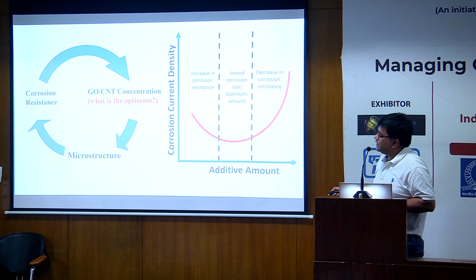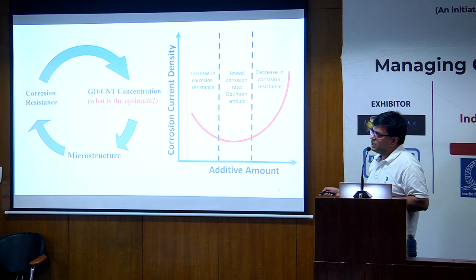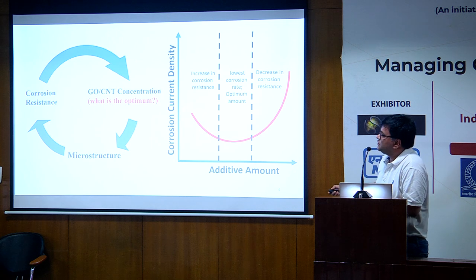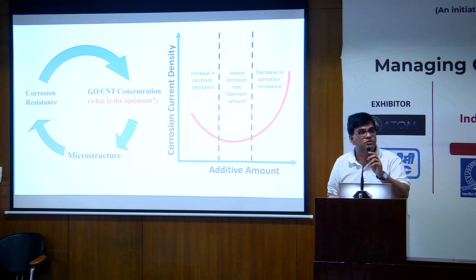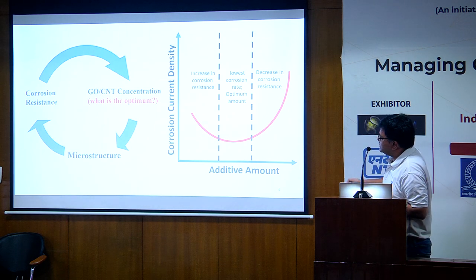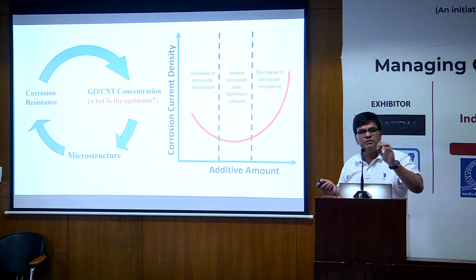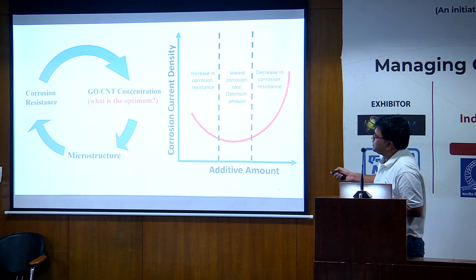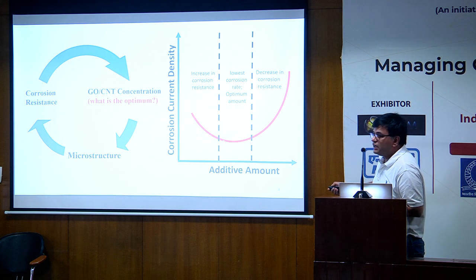What we have done is study the corrosion resistance behavior or corrosion rate of the coatings as a function of the amount of the additive, graphene oxide or carbon nanotube, that we put, and we have connected that to the microstructure and studied this correlation. I'll show you one example to illustrate how this correlation works. This is a general curve that we obtain in our lab for many systems. This is the corrosion current density and this is the additive amount, and we see that the corrosion resistance first increases with addition of the additive,